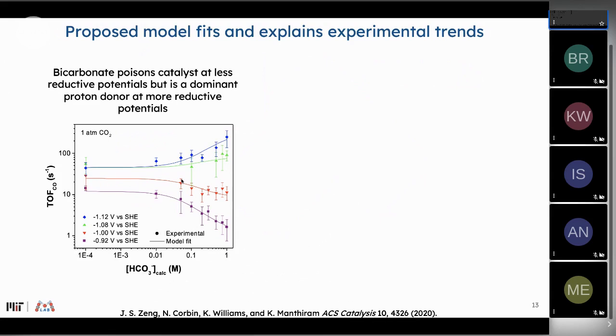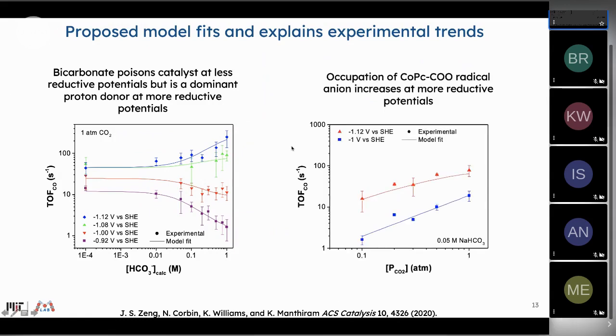And what we see here is that as we increase the bicarbonate concentration at a lower overpotential, that bicarbonate is poisoning. But as we go to a higher overpotential, that bicarbonate is electrostatically repulsed from the surface. And that in turn means that we no longer see a decrease in turnover frequency at higher bicarbonate concentrations, but an actual enhancement in turnover frequencies as the bicarbonate starts to act as a proton donor instead of a poison for the catalytic site. So we can extract this from the underlying model.